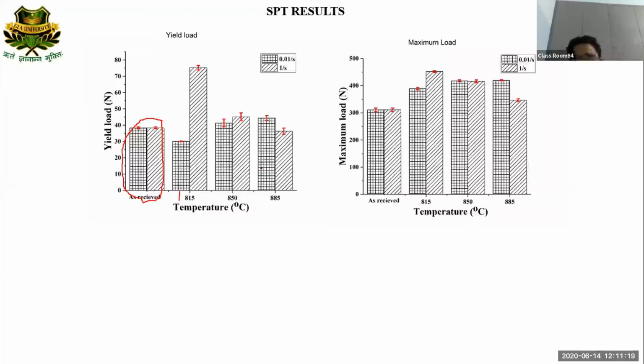Okay, so all the bars are almost clear. This is 850 at 10 to the power minus 2 strain rate, and this is 850 at 1 strain rate, and again 885 degrees centigrade at 10 to the power minus 2 and at 1. And similarly, this is the maximum load of the samples which were deformed at the corresponding different processing conditions. Okay.